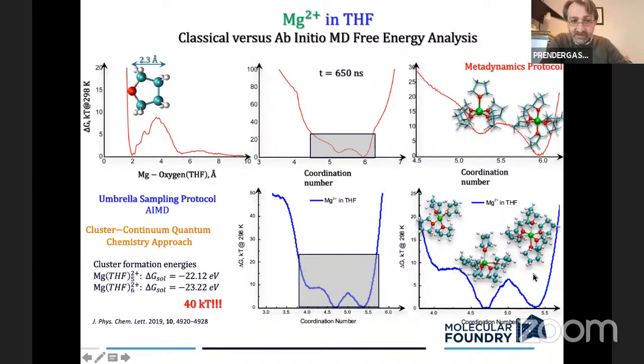That's really surprising, because if you think about it, I said already, these individual bonds between the magnesium and the oxygens of the solvent account for a lot of energy, a lot of enthalpy. And so if you were to just use clusters and compare 6-fold and 5-fold coordination, the difference would be on the order of 40 times kT, even though here we see the difference is 0. There's a barrier, but they're equivalent in free energy, which means there's a 50-50 population of these objects in solution. So that's interesting and very surprising. It must imply that one of these structures is more dynamic than the other, because how otherwise could you have a free energy that is equivalent if the enthalpy is different by such a huge amount?